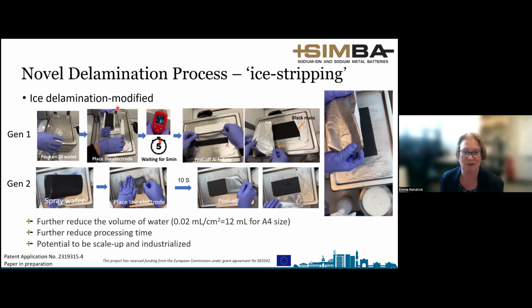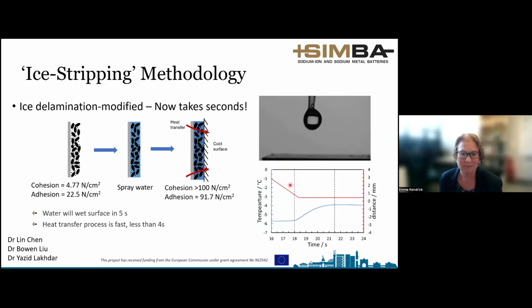Initially, we'd pour water on, we'd lay on the electrode and we'd pull it off. Just by spraying the water on, we can reduce the time that it takes to freeze quite significantly to about 10 seconds, which means we can start to think about incorporating this in potentially a reel-to-reel or in-line process for delamination. And it's quite a simple method.